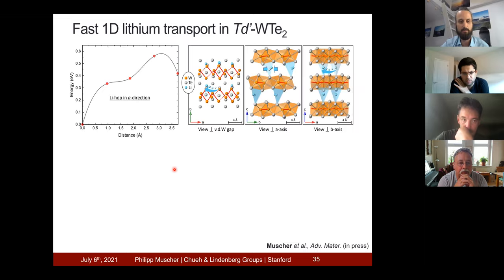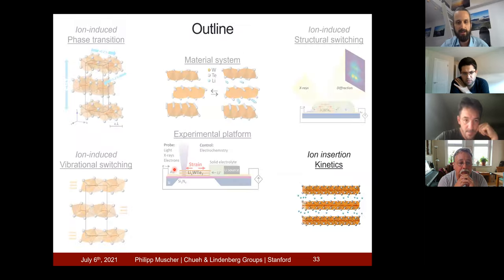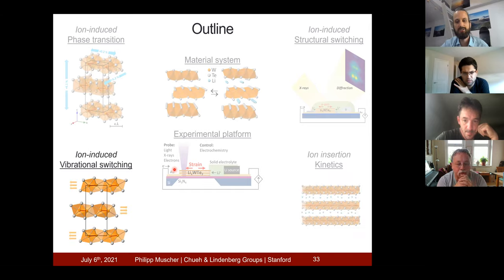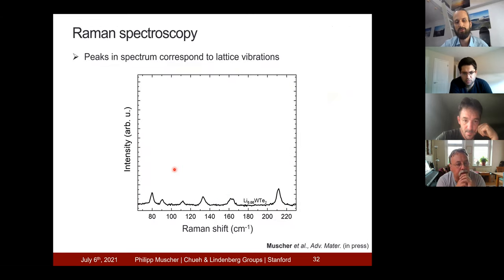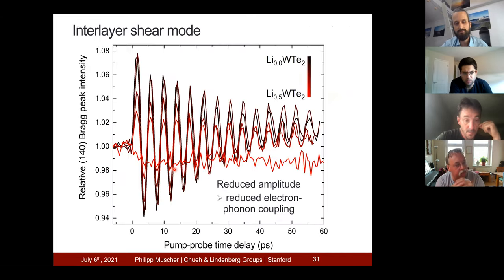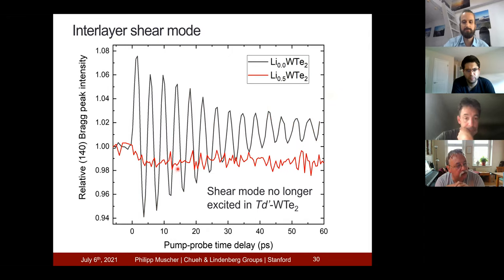Yeah, thanks for the great question. I think one way to distinguish it could be to change the excitation mechanism between a resonant and non-resonant excitation mechanism. This vibration is taking place in the terahertz range. So we could do a terahertz excitation and see if we're then able to excite that mode. That would be my idea. Okay.